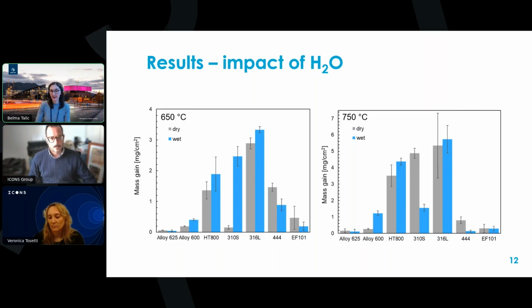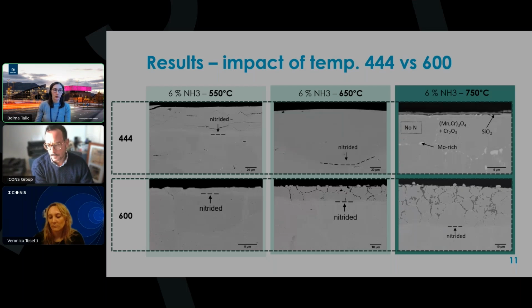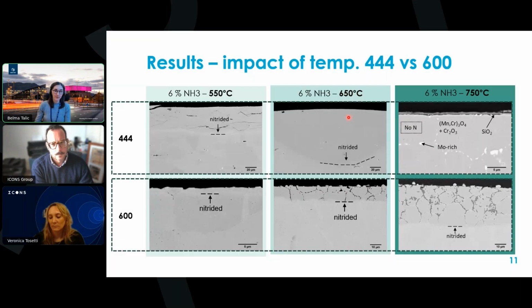But what we can say is that when we compare our SEM analysis, so looking at the depth of nitridation and the amount of nitrogen dissolved in the alloy, and compare that to the mass gain data, there's a very good correlation between the two. So the majority of the mass gain that we are measuring is because of nitrogen going into the alloys.